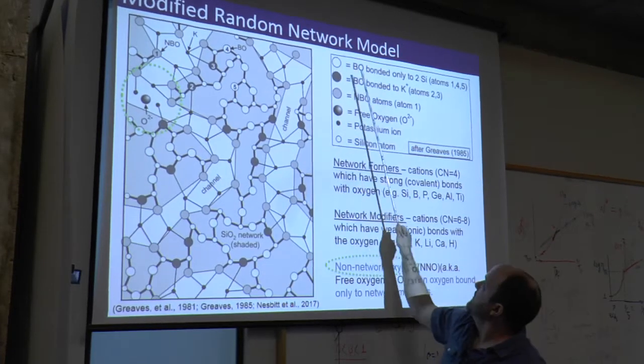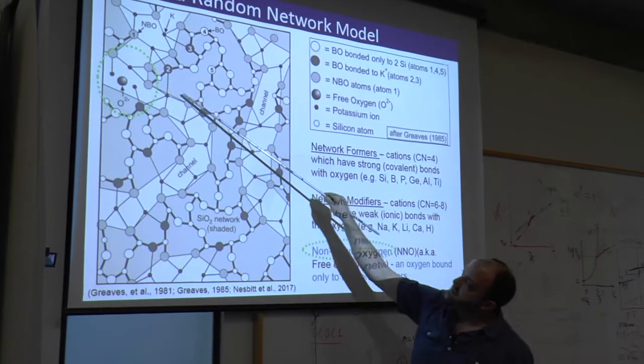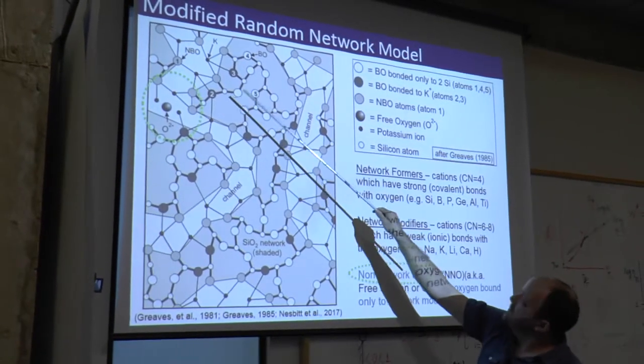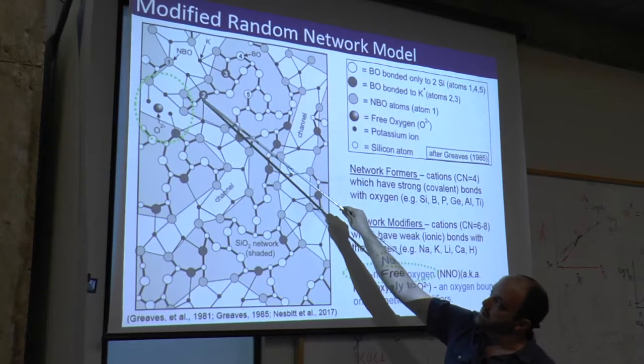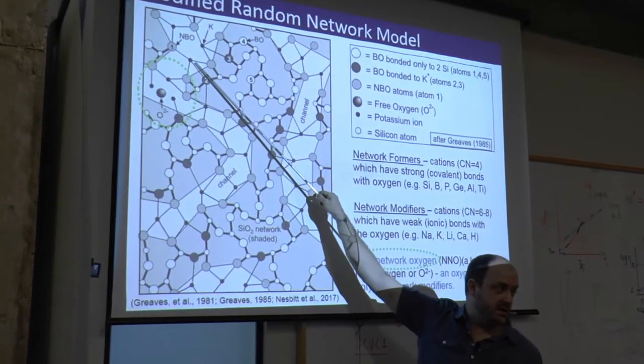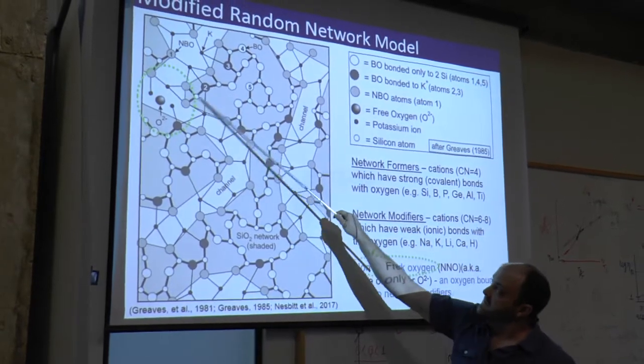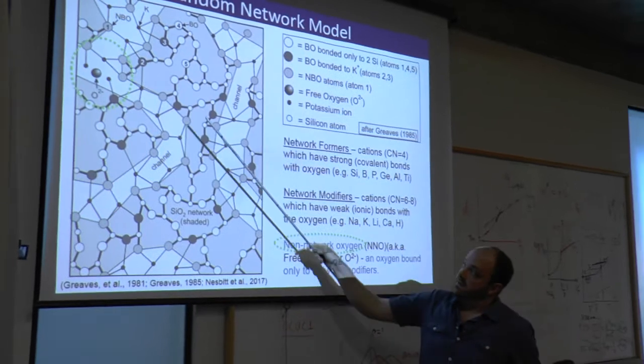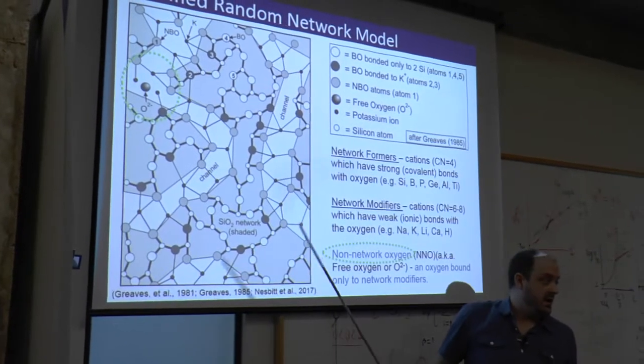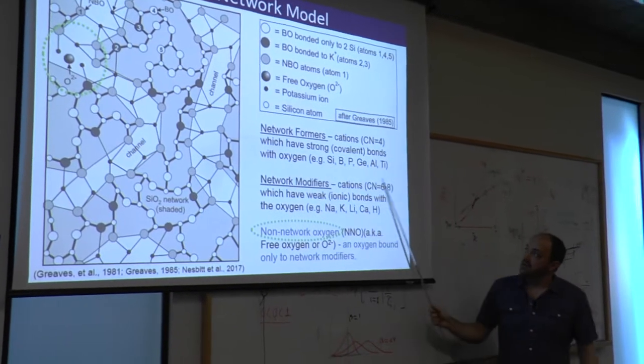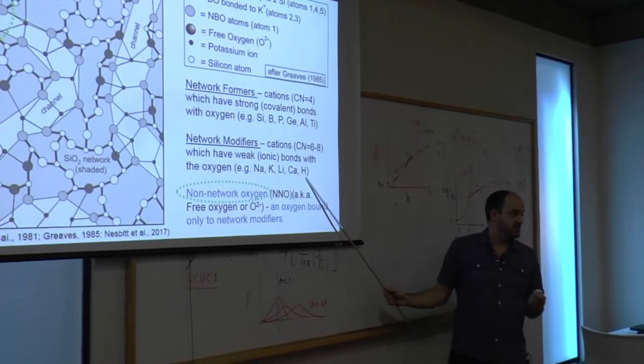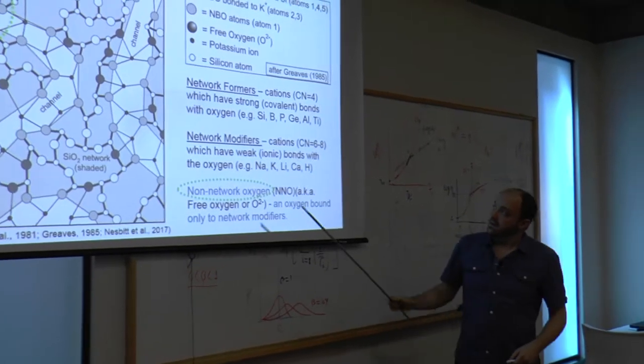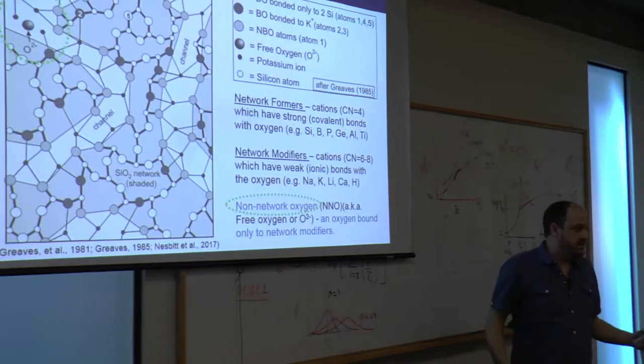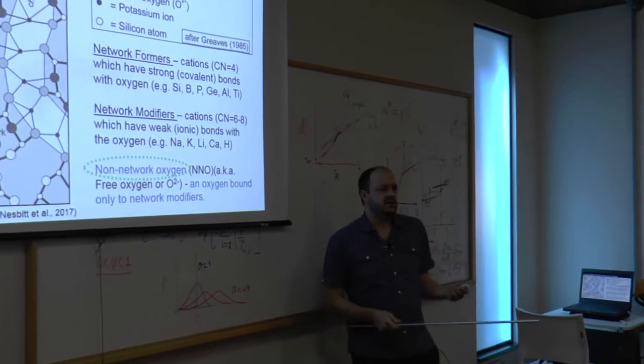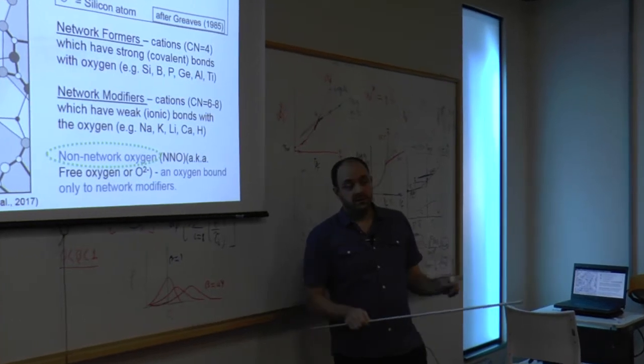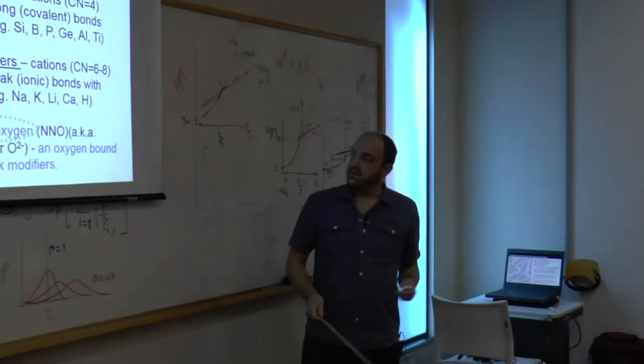This guy as well. If we look at some of the oxygens around the margins of this silica-rich network, for example, oxygen 2 here, it's bound to 2 silicons, but it also has this modifier sitting beside it. So this is the major development by Greaves. He said these modifiers actually have some order, and if they have a coordination number of typically 6 to 8, they must be sitting next to some bridging oxygens. That was a big deal, because it means you have to take this into account when you're making any model. You can't just say the oxygen is bound only to silicon. It has to take into account this modifier effect that's sitting nearby.